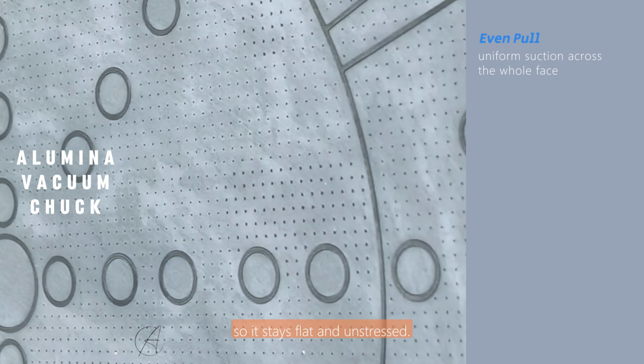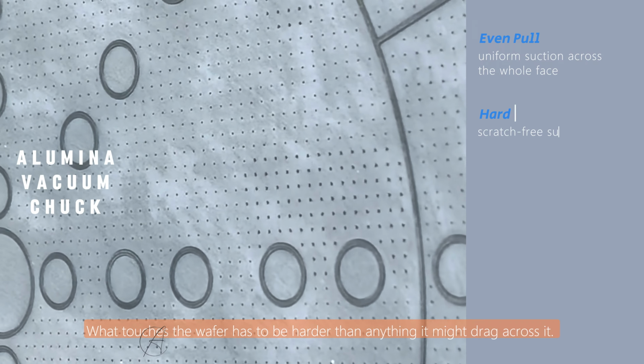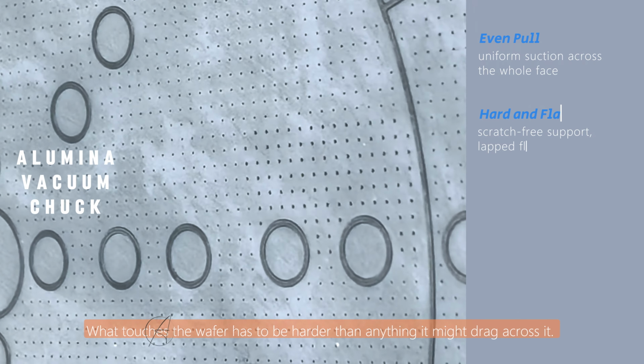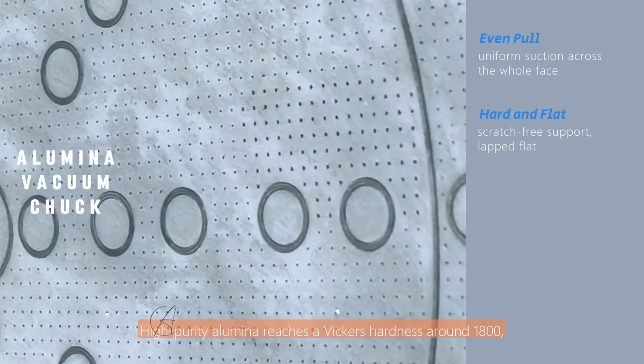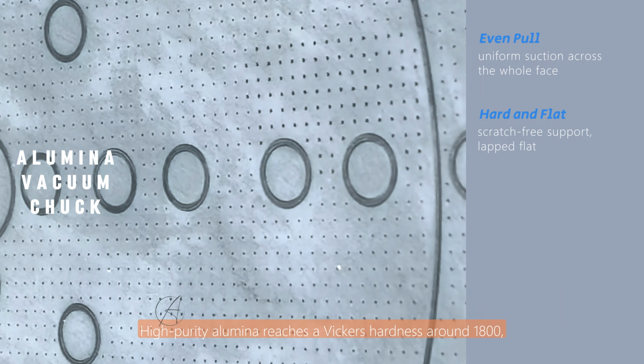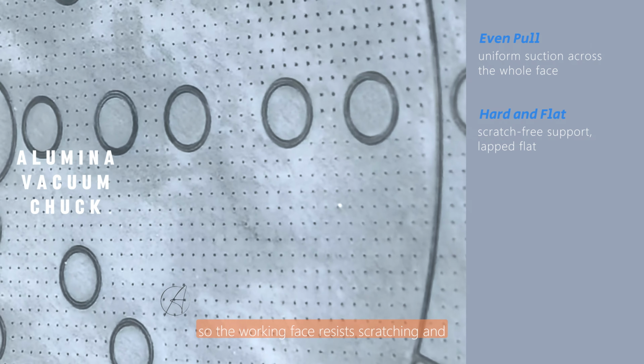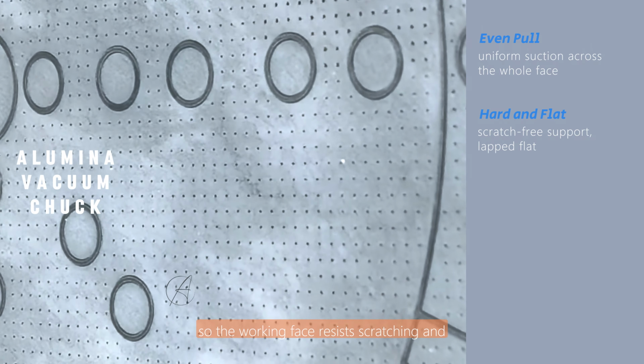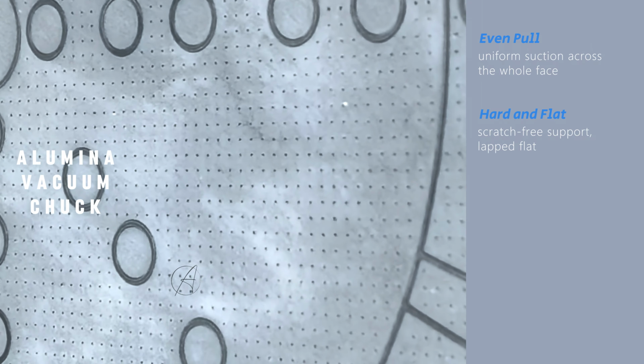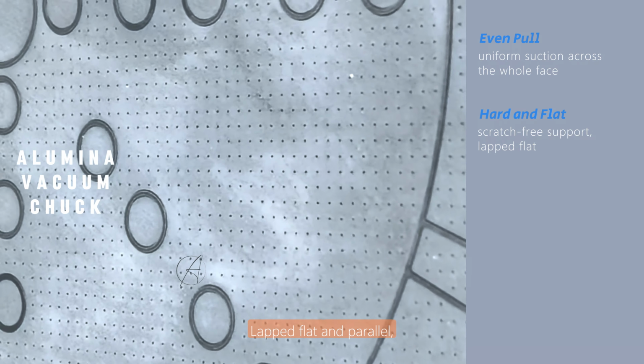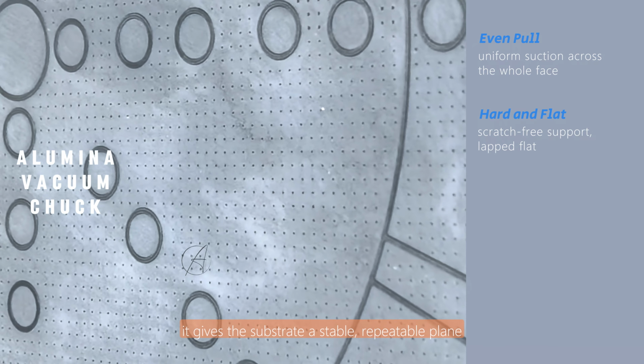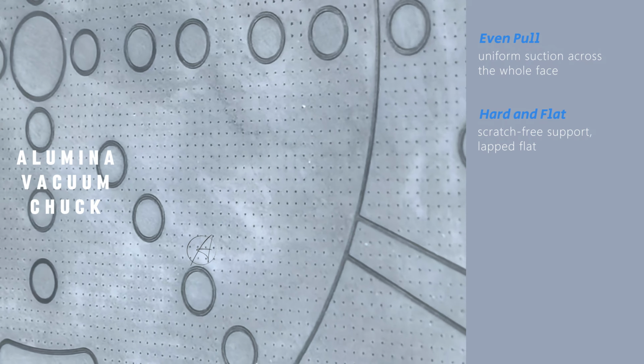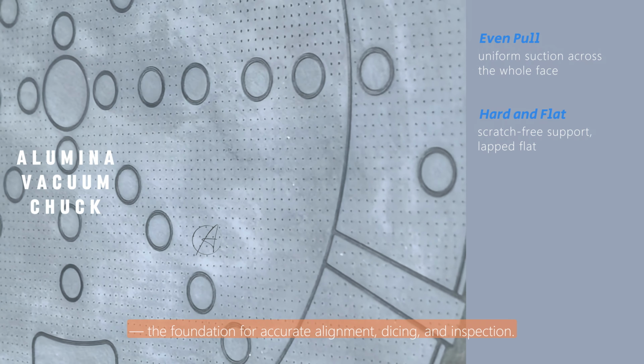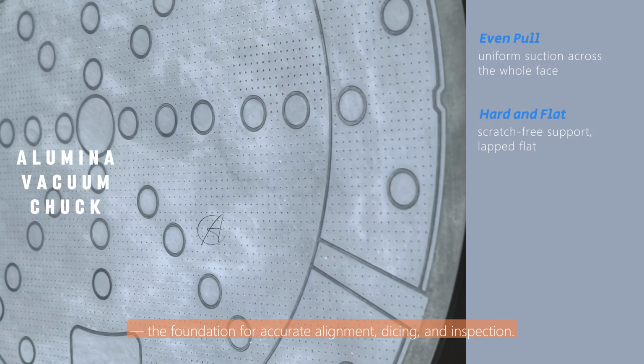and unstressed. What touches the wafer has to be harder than anything it might drag across it. High-purity alumina reaches a Vickers hardness around 1800, so the working face resists scratching and wear through countless cycles. Lapped flat and parallel, it gives the substrate a stable, repeatable plane. The foundation for accurate alignment, dicing, and inspection.